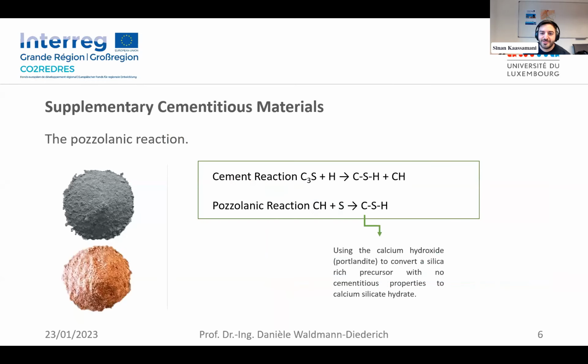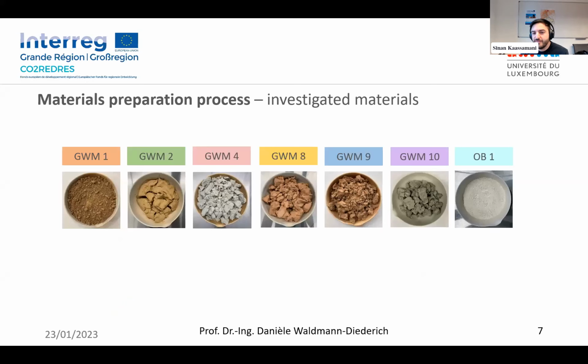So first of all, I would just like to remind what the pozzolanic reaction is, something that we were looking for, right, in these materials as substitutions. So we wanted materials with this potential to be able to react with calcium hydroxide and to get more CSH, let's say, into our hardened pastes. So the materials that we studied were 7, even more, but then the ones that we kept until the end of the project were 7. So these were the ones that had potential to be used as SCMs.